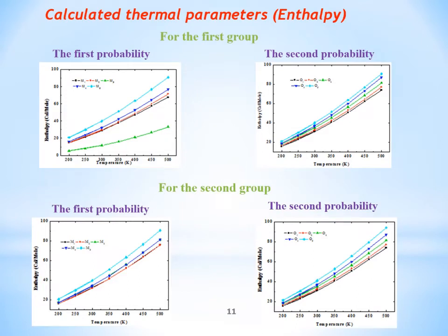Thermal parameters. We will calculate some thermal parameters, like enthalpy. Enthalpy is defined as the sum of the system's internal energy and the product of its pressure and volume, and expresses released or absorbed energy. In the first group, for the first probability, we see that the low values of enthalpy are with addition of 2 units of zinc oxide to the PVA sodium alginate blend. By comparing this result with the second probability of the first group, and the second group with first and second probability, we find that the low value is the first probability in the first group with addition of 2 units of zinc oxide, and the interaction may occur through the zinc atom.